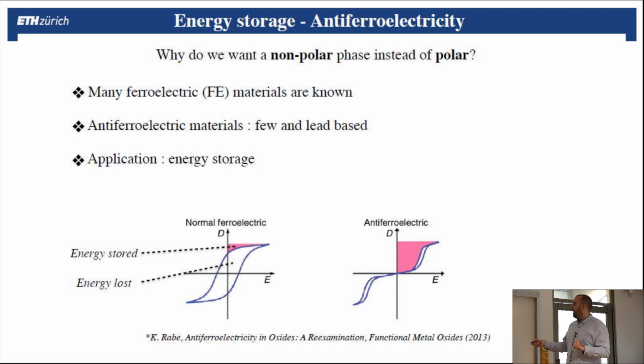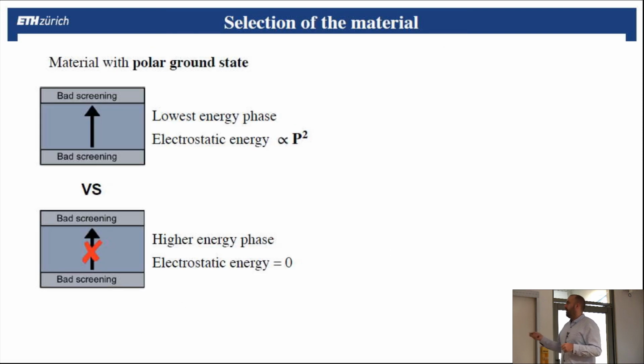But when you remove the field, you go back to 0. But what is interesting is that you can store more energy here in that case. And that's why antiferroelectric materials are interesting. And there are not so many. And the problem also is that they are usually composed of lead, which is bad for the environment, and people are trying to get rid of it. So that's the motivation of having this non-polar phase instead of the polar one.